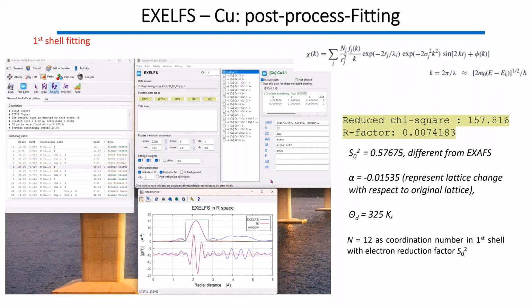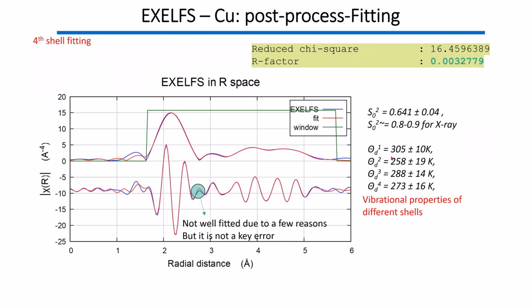Okay. And with this setting, you can include all of these paths and fit up to the fourth shell. In that sense, because we are fitting more shells and the statistics are better, we have a slightly different result compared to the fitting with only the first shell, which tells us how important it is to have good data quality so that you can have this factor calculated properly. And also you can see the Debye temperature difference between different shells, which is very consistent with what X-ray measures.